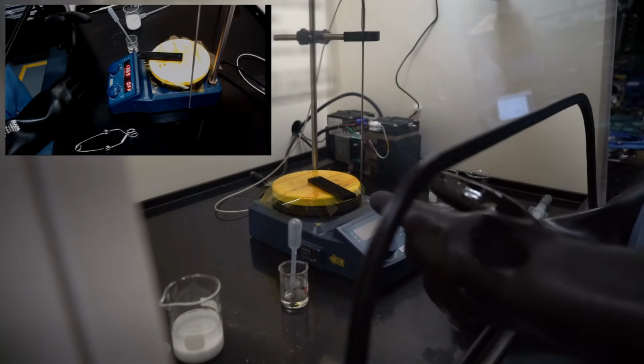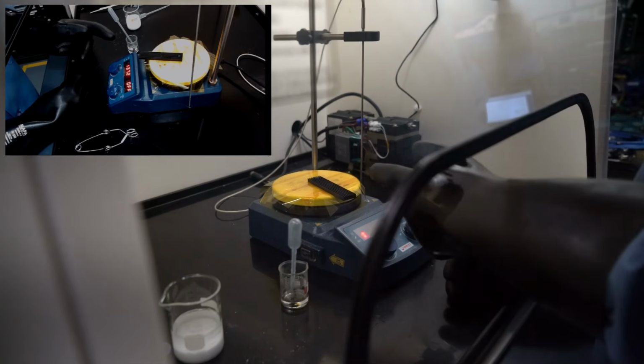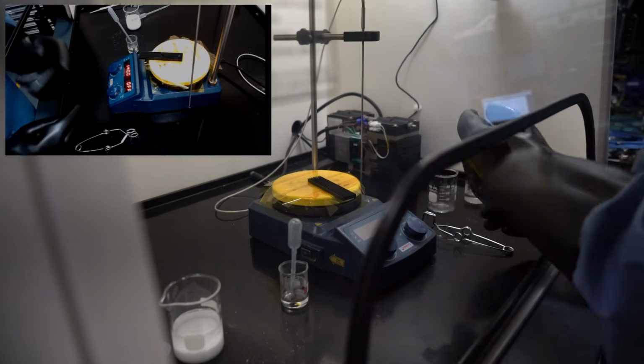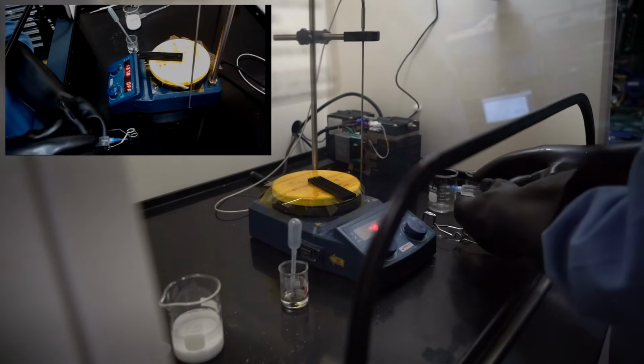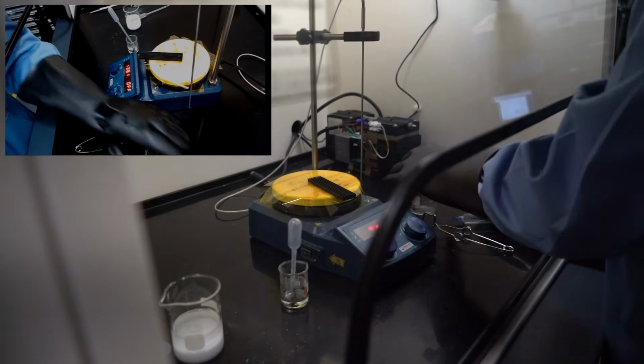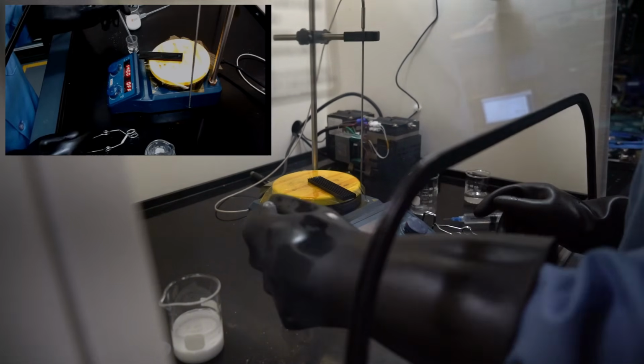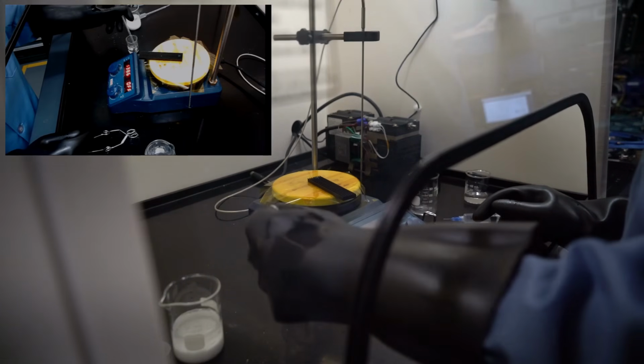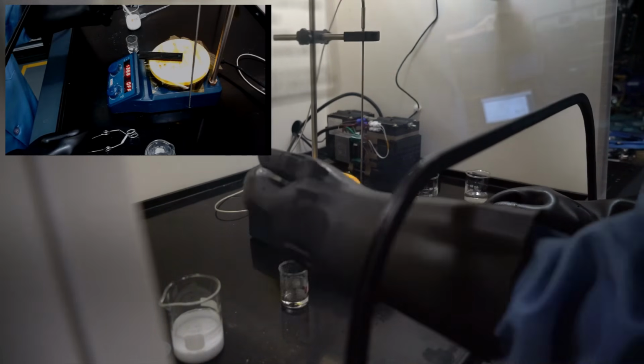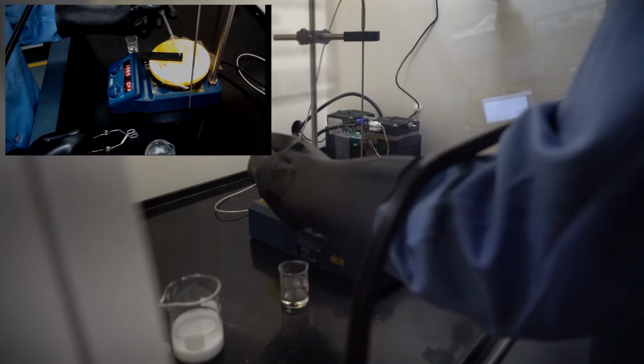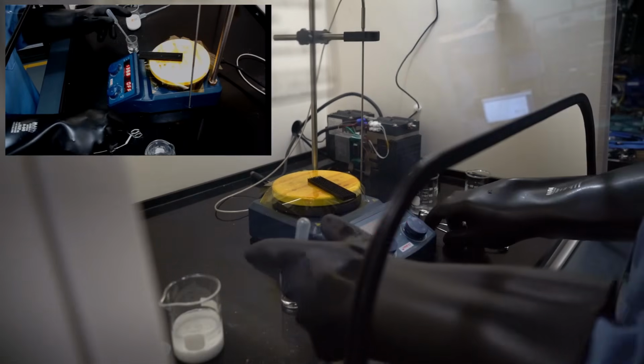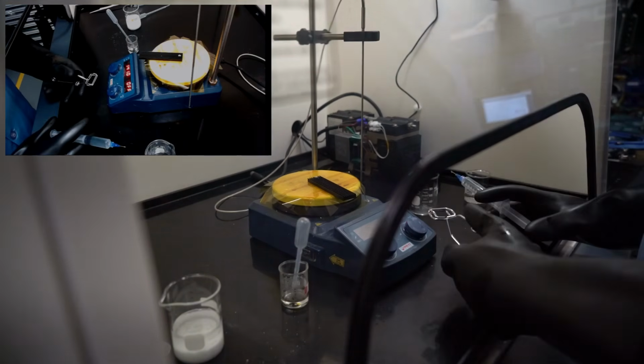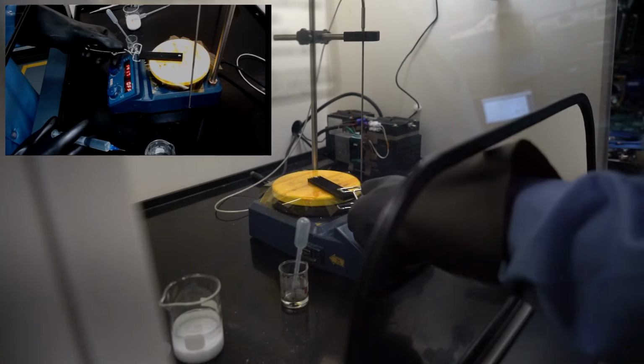And now we've got our acid mixed and we've got the sample preheating. We have the cleaning solvent, which is just acetone prepared in a syringe with a blunt needle for rinsing. This allows a much higher pressure stream than you would get by just swishing the sample around, and also goes through solvent a little bit slower than in a wash bottle, and actually allows higher pressure in some cases. So now we've got the acid on the sample and we're letting it sit there and react.